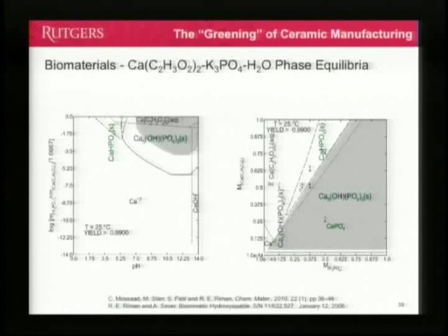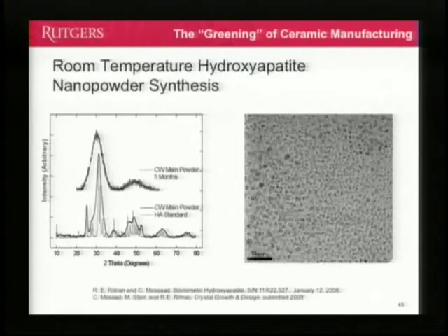And here's, again, she did the modeling, and the experiment showed that she could make a material that is some of the smallest particle size hydroxyapatite in the world. It's about 2 or 3 nanometers. The material is so unstable that if you let it sit for 5 months, it does something that ceramists think is unthinkable. You go from a crystalline material to being an amorphous material, because there's so much surface there. There's more atoms on the surface than there is in the bulk, so the whole thing just goes disordered, and the crystallite size actually decreases by a factor of 10.